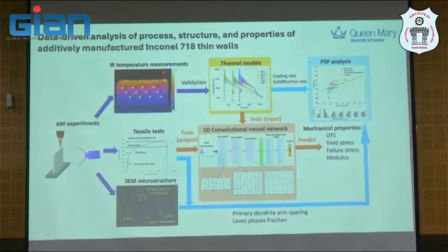They have infrared temperature measurements at different locations. As I told you before, each location has a different thermal history. So they extract this thermal model, validate it with IR thermal imaging, and then get the analysis of the cooling rate and solidification rate for property prediction. I will tell you what they did. They predict UTS, yield stress, failure stress, and modulus based on the thermal data they get. They use a 1D convolutional neural network to extract those features. They can even predict primary dendrite arm spacing, which is important for the property later as well.